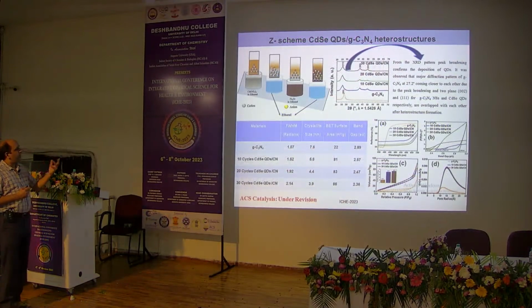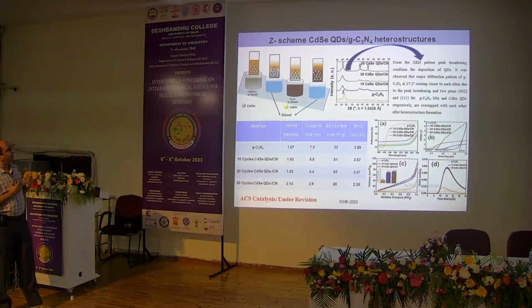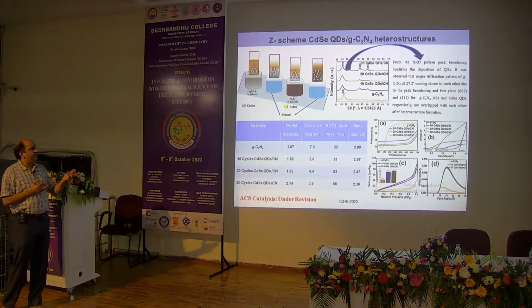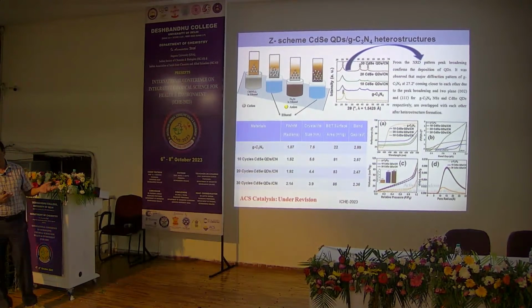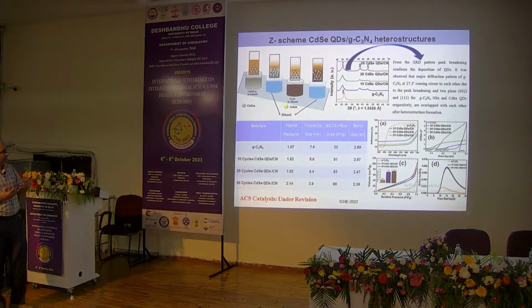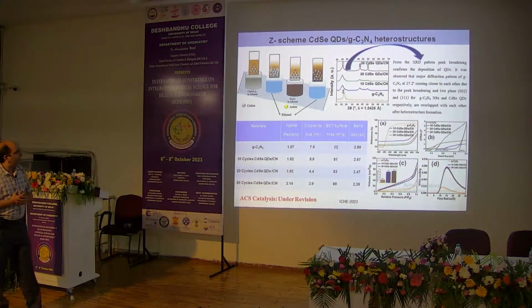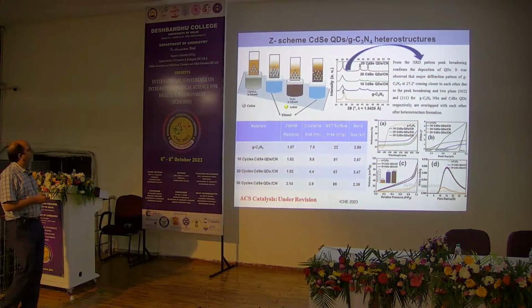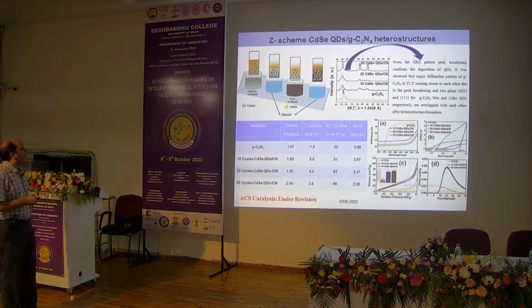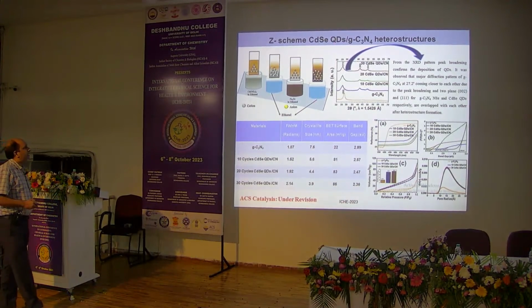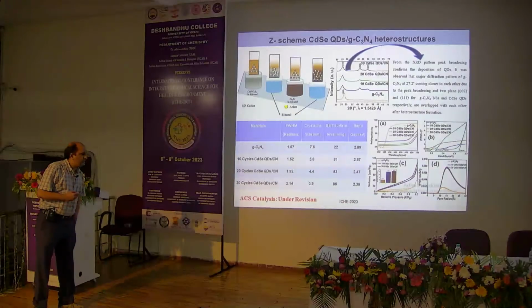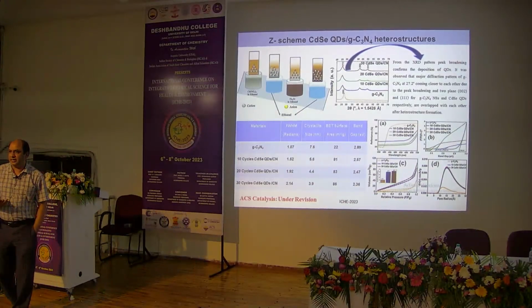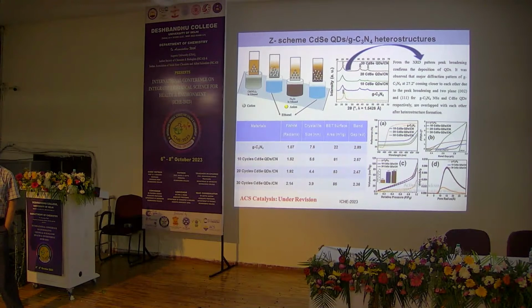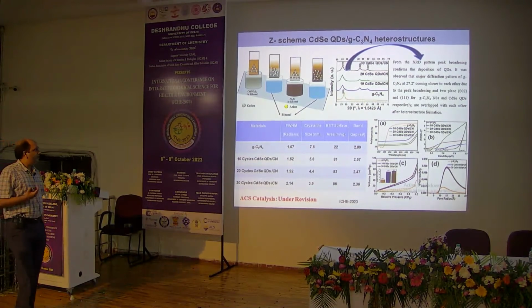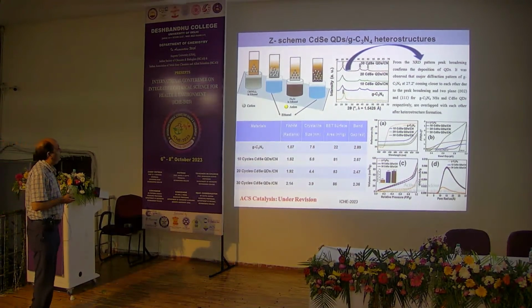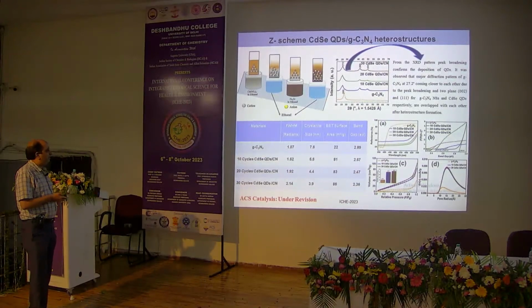This is the heterostructures of the cadmium selenide quantum dots with graphitic carbon nitride, and this paper is under consideration. In fact, we have submitted the revision part in ACS Catalysis. We prepared these CdSe quantum dots by using the SILAR method, and we applied 10, 20, and 30 SILAR cycles for the formation of the CdSe quantum dots, and then mixed with the graphitic carbon nitride, and these are the primary investigations.